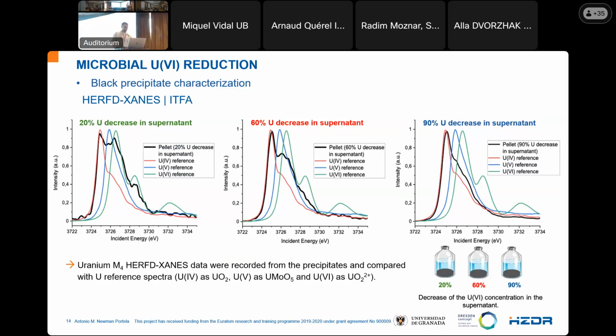Using the same samples, the 3 different samples with a different uranium decrease in the supernatant, I would like to focus on the last one. Here, this result shows the data recorded by HERFD-XANES and compared to the different uranium references. We have a reference for uranium-4, 5, and 6, and the black line is our sample. This peak fits with uranium-4. So there is a dominance of uranium-4 at the end of the experiment, as we observed before. But there is a peak here that corresponds with uranium-5. So we identify uranium-5 in our samples.